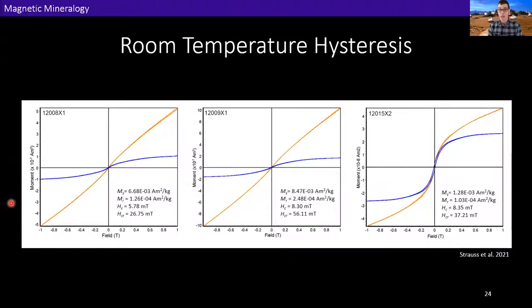I've also pulled out some of the parameters that we use to define the shape and size of each of our loops, and I will come back to that very shortly. So our measurements were dominated by diamagnetic and paramagnetic contributions, probably because we were using very small samples for these particular experiments. But we did also observe some open loops that we thought could be suggestive of multi-domain states. And I want to note that they could also be explained by some combination of having extremely weak samples and some known thermal disequilibrium issues with the particular AGFM that we were using.